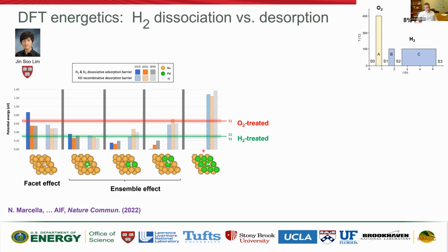And so you see here that, for example, for a large surface of palladium, a monolayer, for example, we have very high effective or apparent activation energy, inconsistent with experiment, either for oxygen treatment or hydrogen treatment. But when you have a trimer, the activation energy predicted theoretically is just right. It's in good agreement with what was obtained under oxygen treatment. So this is consistent with formation of this type of trimers, these palladium ensembles on the surface. And we can say with certainty that trimers were dominating. It was not a mixture of trimers and dimers of some sort, because with dimers we would have much lower activation energy, and we would not be able to easily distinguish between dimers and monomers, because for both of them we would have similar activation energy consistent with experimental data. But it is still a very informative conclusion, because we can pinpoint what ensembles are formed under which regime.